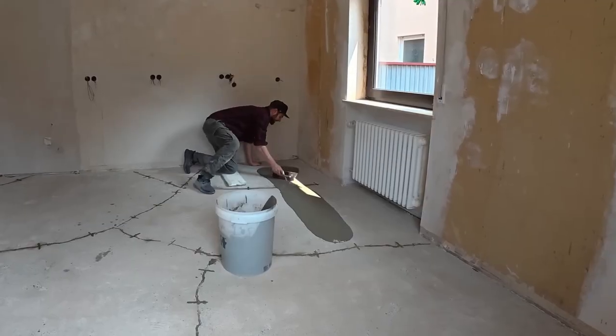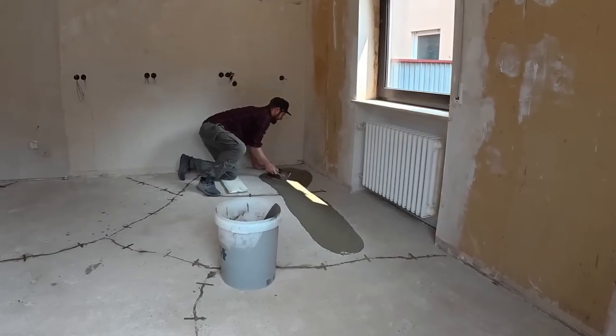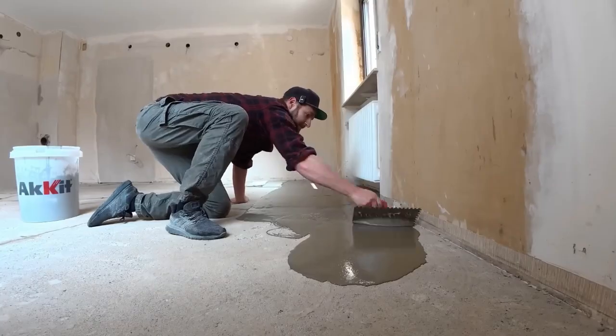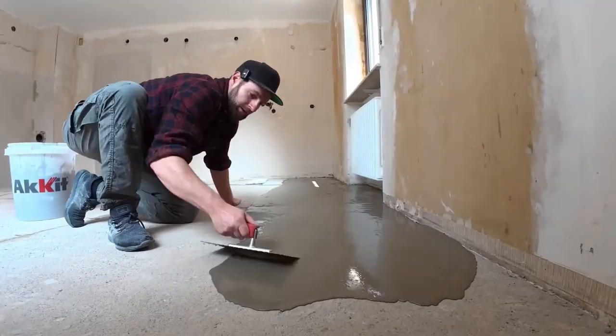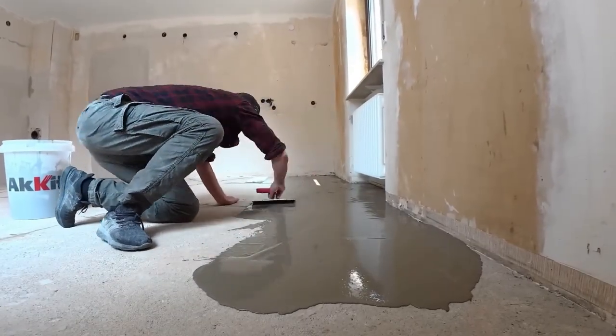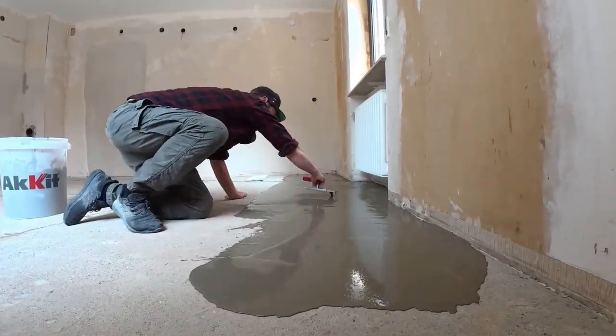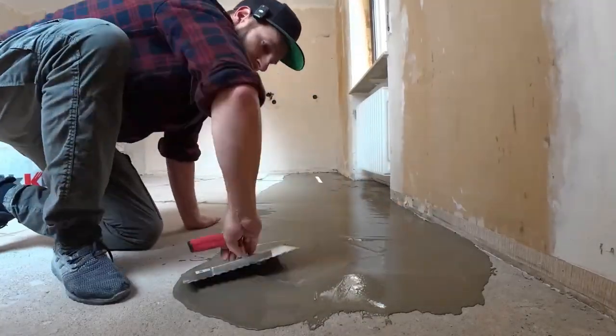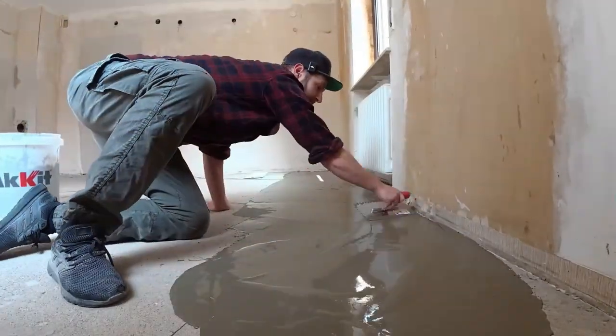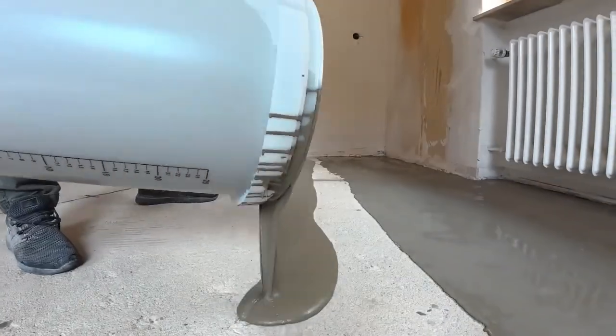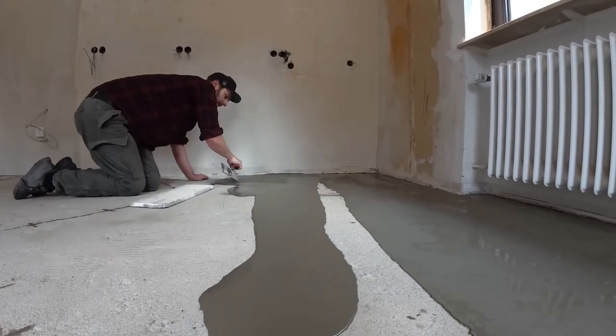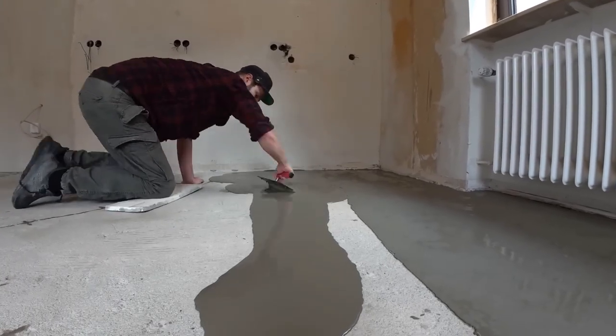Then the application finally started, and the leveling compound set on the floor really quite quickly. I hadn't expected that, and you really have to move fast if you want to get smooth and clean transitions between the individual strips. The takeaway from this job is that, ideally, you should work with 2 people here. One person spreads the compound on the floor while the other is already mixing the next batch, so there's no significant delay between the individual strips.